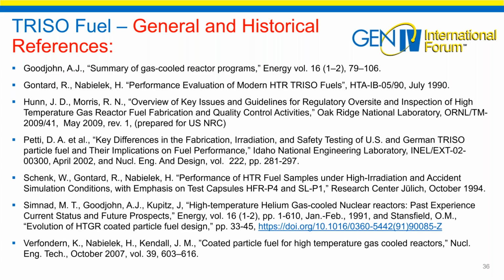So that means that, for instance, as you coat the fuel, you're going to have to take samples from the coater while it's running, it's automatic now. You don't want to stop the coating process, let the particles drop, unload the coater, take some out, and then put it all back in. You want to do this continuously. So this is part of what we did at Oak Ridge and BWXT, to have a method to take out samples as you go along. And so what you do is you take out samples, and for instance, you have to measure the density. We have a sink float method, basically a gradient column with different densities. I'm sure you've seen that as a kid with temperatures.